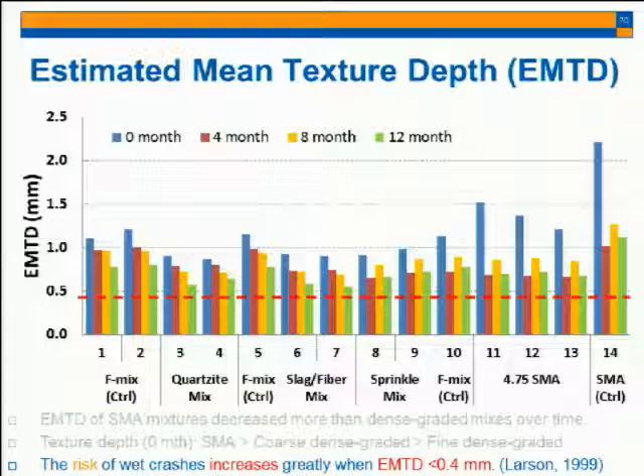Yeah, but there is some recommendation for this mean texture depth. If the mean texture depth is less than 0.4 millimeter, we have a higher risk of wet crashes. All of our sections were above 0.4 millimeter of mean texture depth.